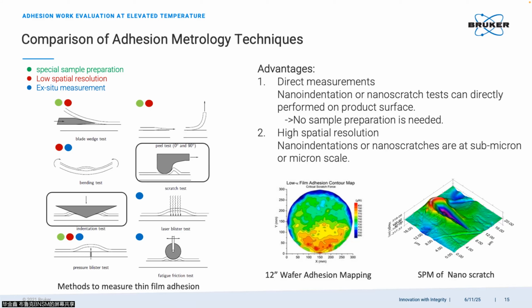That means you have a very high resolution. For example, if we have a delamination just the size of a micron or several microns, you can imagine that for a 12-inch wafer, you can perform a lot of scratches all over your wafer and see the distribution of your interfacial bonding. This is a real example of a data set, which is the scratch result mapping. If my memory is correct, it was created from more than 1,000 scratches all over one single wafer.